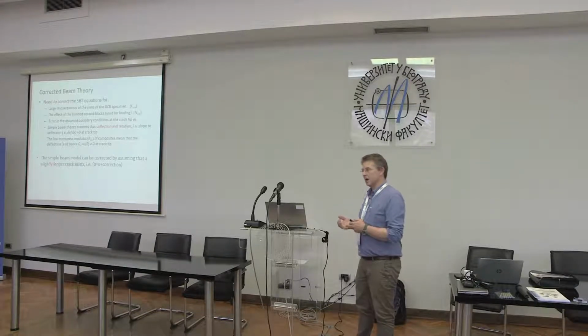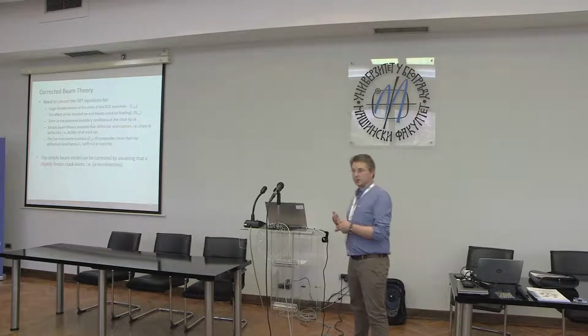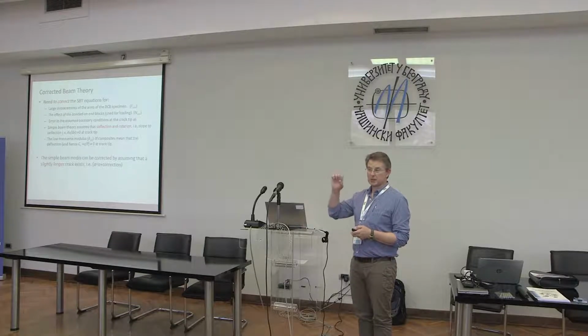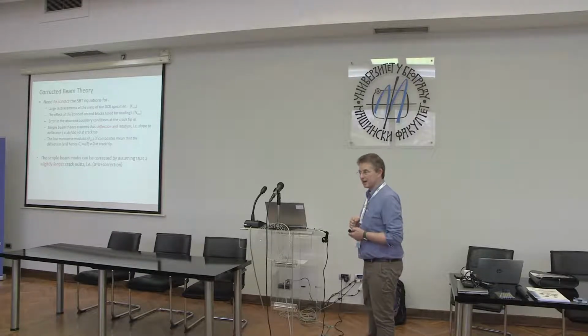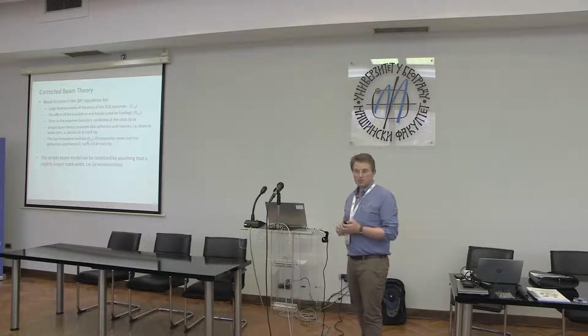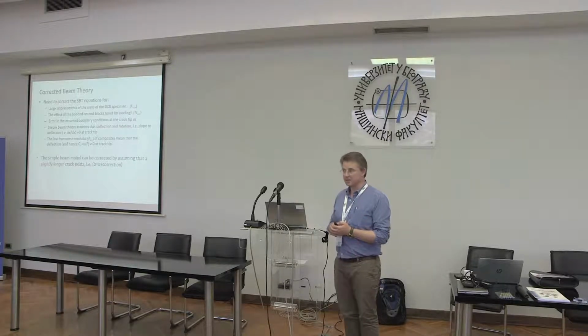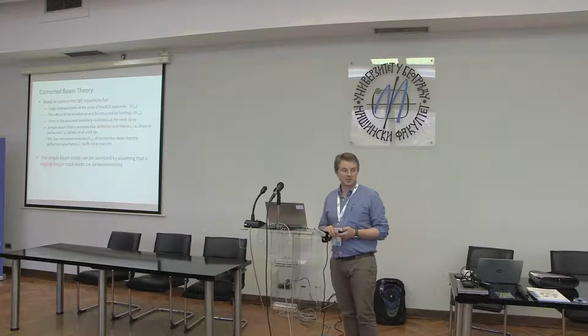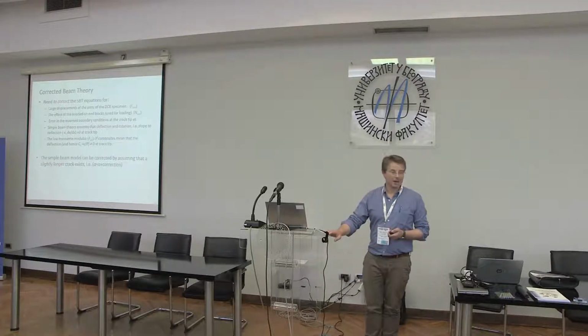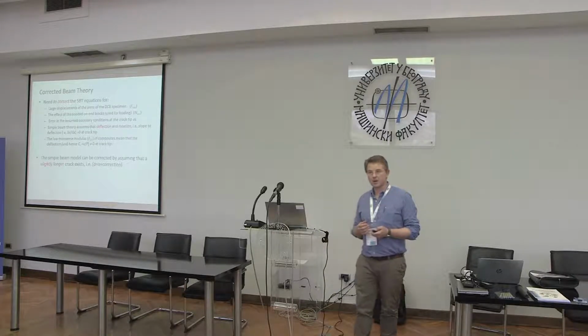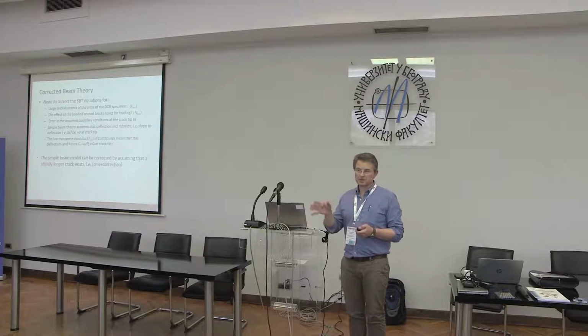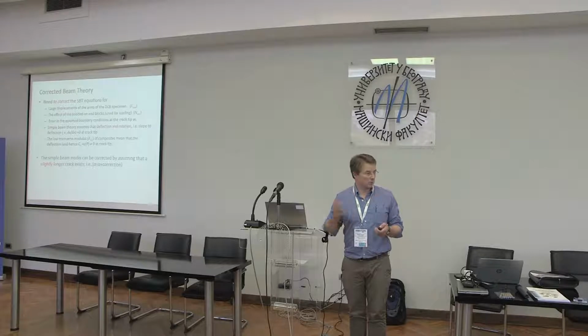Of course, a number of things were wrong, but the most critical thing that was wrong was that assumption that the specimen was built in at the crack tip. Okay? Because the specimen is not built in at the crack tip. The specimen is free to displace and rotate at the crack tip. So that had to be taken into account. That's particularly true with the relatively low transverse modulus of the materials that we're talking about.